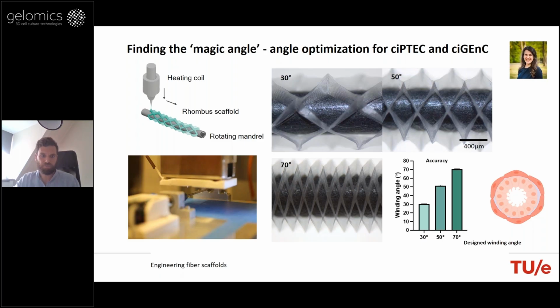In collaboration with colleagues from Utrecht University, we printed tubular structures with different winding angles that span from 30 to 70 degrees. And then we cultured both conditionally immortalized proximal tubule epithelial cells on these and conditionally immortalized glomerular endothelial cells on these. And then we tried to find the magic angle that would allow to create a monolayer of cells inside of these tubes, and their organization, that is also crucial for the function of these proximal tubules.